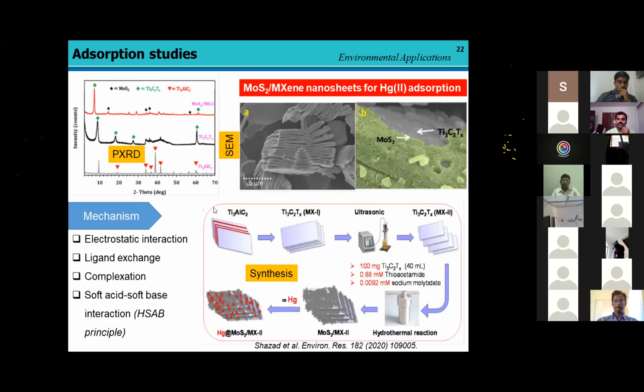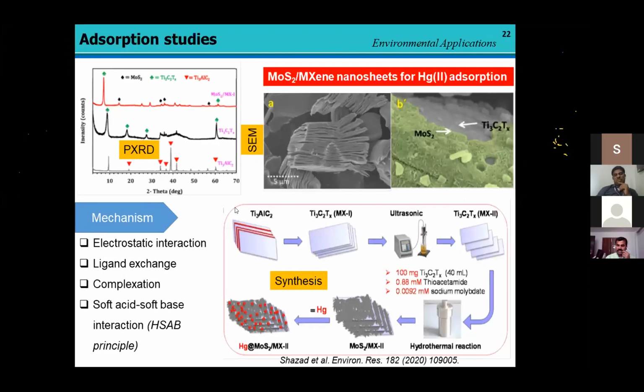which was applied for the development of molybdenum sulfide on the surface of MXene by a hydrothermal method. Then we confirmed that the molybdenum sulfide was intercalated between the layers rather than deposited on the MXene phase by XRD results. Then the mechanism was explained well: mercury was adsorbed on the MXene phase through electrostatic interaction, ligand exchange, complexation, as well as soft acid soft base interaction. Since molybdenum sulfide has a sulfur moiety, which is a soft base, the soft acid mercury will interact easily. The soft acid soft base interaction happens with the help of the HSAB principle.